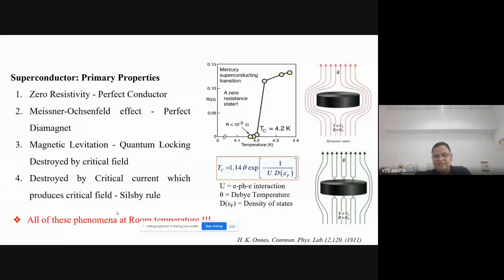Then came the Meissner effect, Ochsenfeld and Meissner. That depends upon this thing, which is independent of R equal to 0. If you apply magnetic field on a superconductor, then below a critical field, as you see in the upper panel, all magnetic flux lines are excluded from the interior of the superconductor, and no magnetic flux lines pass through it. But if it reaches beyond a certain critical field, some of the magnetic flux lines pass through the superconductor, and that is called the mixed state.